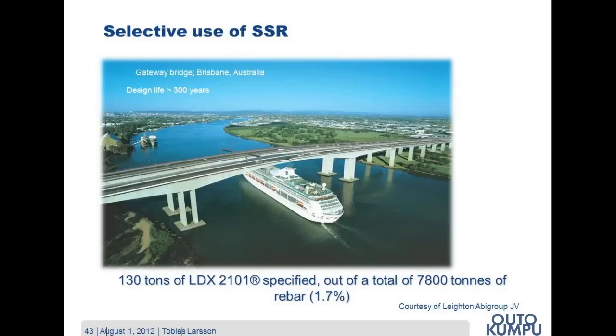Since the way forward for successful companies is to find the most cost-effective solutions, our advice is to use stainless steel rebar selectively in the most critical areas. In this case, for the Gateway Bridge in Brisbane, Australia, it was used in the outer layer of the bridge piers, located in the sea. So in total, 130 tons of stainless steel rebar out of a total number of 7,800 tons of rebar used was specified in stainless steel.